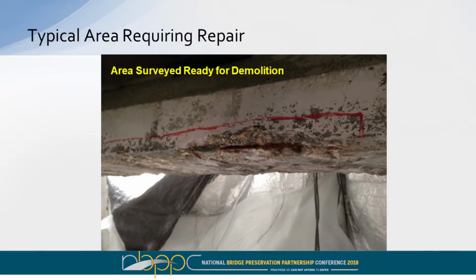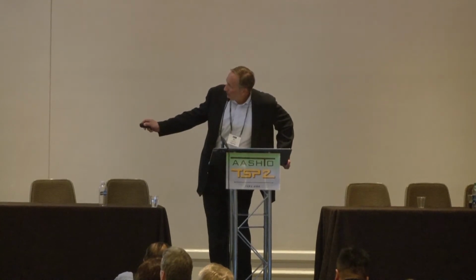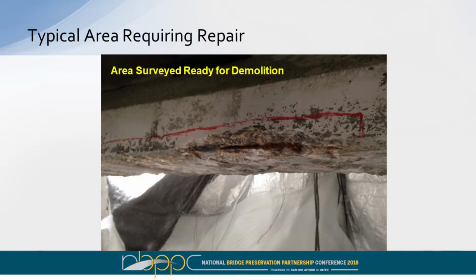So underneath the structure, you can see obviously the first part of our job is to start surveying the areas that were showing some deterioration, marking them off with red lines and so forth, orange lines, and starting to chip away that gunite that was found on the bottom of the flange. In this case, we removed the gunite. You can see some of the poor condition of the material that was already in place. And of course, you can start to see some of the condition of the pre-stressed strand.